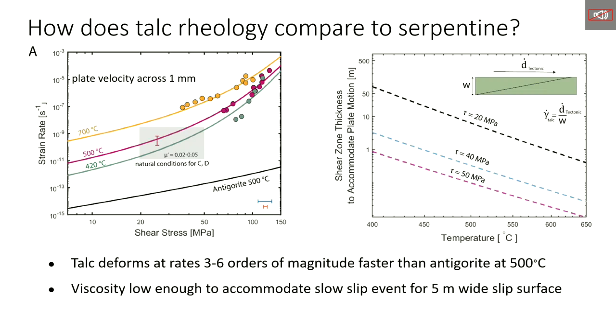And some other work that Hannah is doing indicates that as you get near the transition to where talc starts to dehydrate, you pump up another couple of orders of magnitude decrease in viscosity. But it was really important for us to do these tests because we know talc was weak, but now we can quantify it.